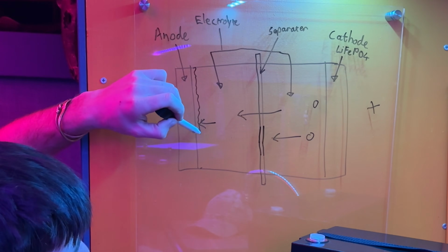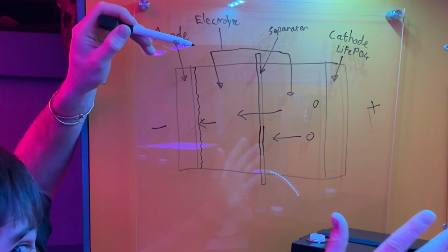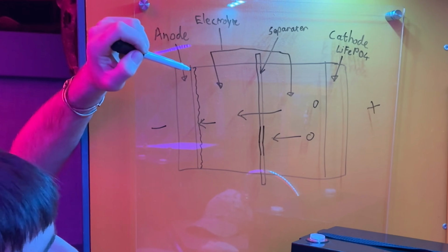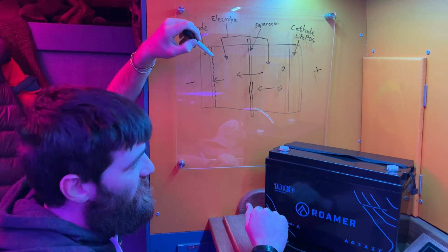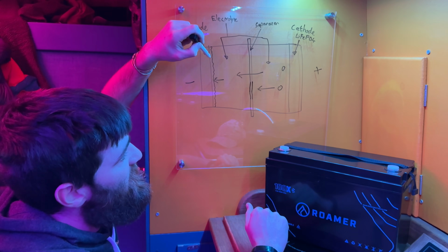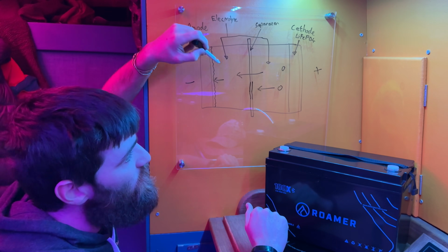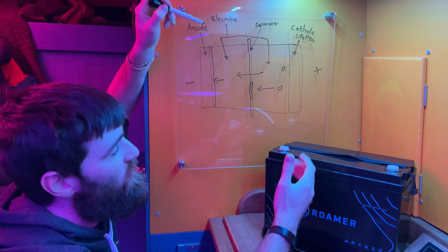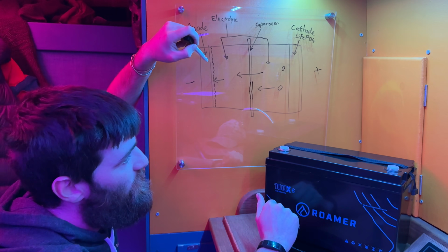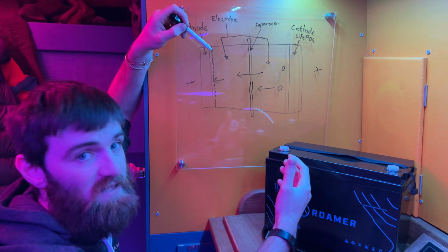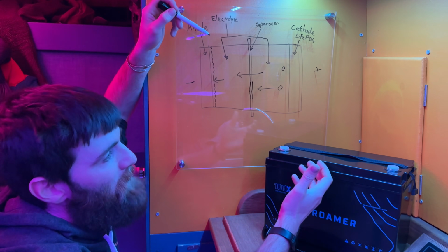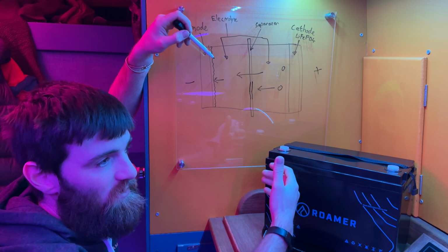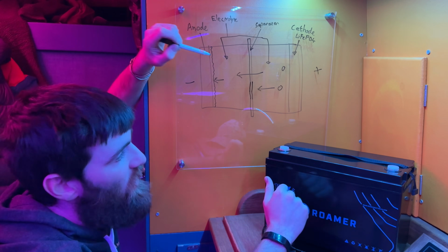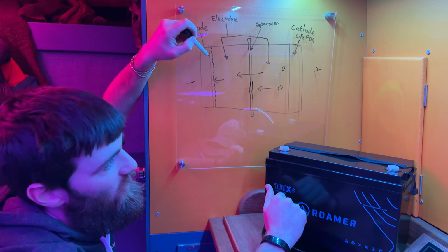And that will form a lithium plating over your anode, and that's the damage you'll cause to your lithium battery by charging it cold. That plating, one, prevents the lithium ions from being absorbed into the anode, and also removes useful lithium for your charging, turning it into a metallic form. So the damage you're doing is decreasing the amp hours, or the watt hours, or the charged capacity of your battery, because you've changed the state of the lithium.